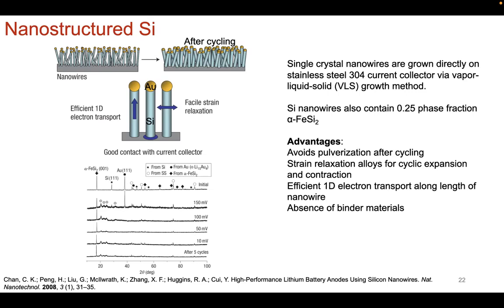Okay, so that's a shift in design. And why this was looked at is because the nanostructure will help you avoid pulverization that's been observed for larger size particles, like the micro-sized particles that we just talked about. Now, what is acknowledged is, of course, you might have a little bit of reduced capacity because there's some phase impurity. In fact, 0.25 phase fraction, so 25% of your material is this alpha iron silicide, but the other 75% is the silicon that you're desiring to grow.